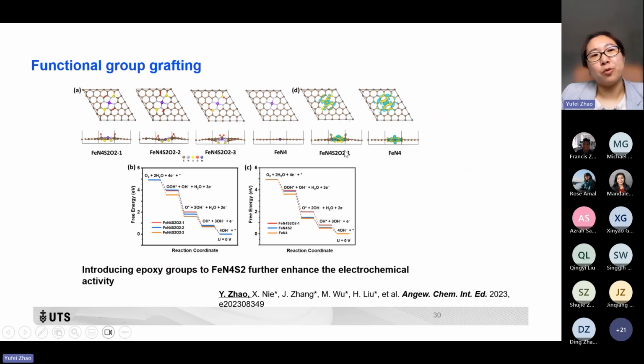And based on this atomic structure, we further try to incorporate other functional groups to improve the performance. We have used DFT to incorporate these epoxy groups. We have constructed 3 different structures by incorporating these epoxy groups into this iron, nitrogen 4, sulfur 2 structure. When we put the epoxy group here and here, this is called structure 1, structure 2. For the third structure, we have put the epoxy groups on top of this carbon and the sulfur atoms. But after the optimization, we found the first 2 structures are quite stable, and the third structure is not stable. The bond between the oxygen and the sulfur will break.